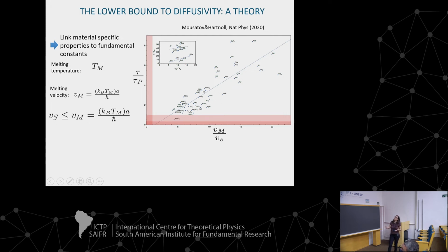To prove that this model makes sense, they took a certain number of secondary data and tested if the model holds. And they showed that, in fact, there is a quite close relation between the proximity to the Planckian time and the proximity of the sound velocity to the melting velocity.